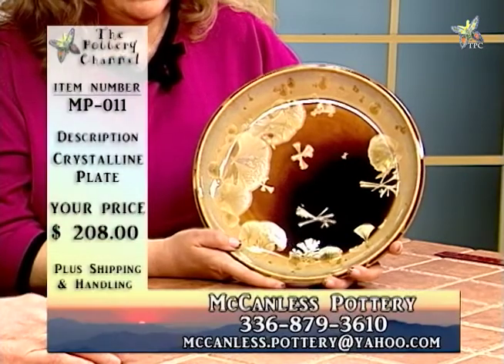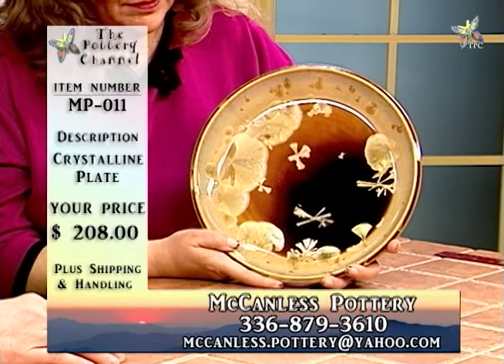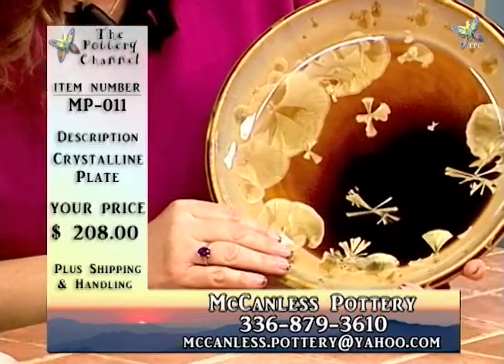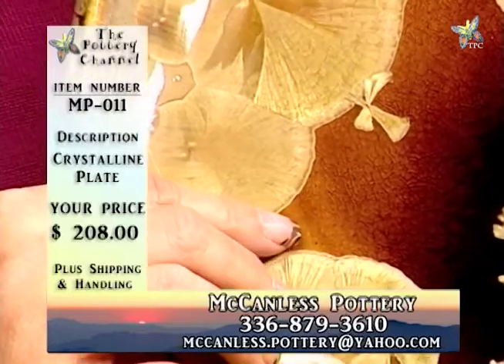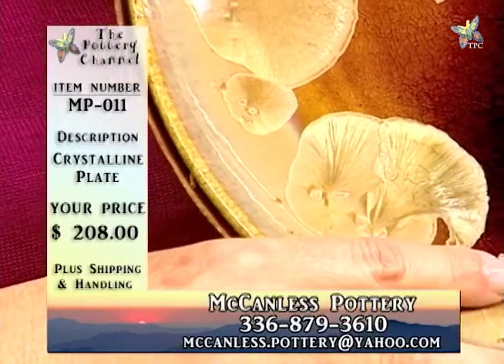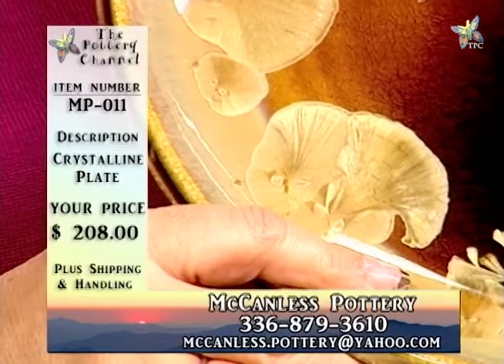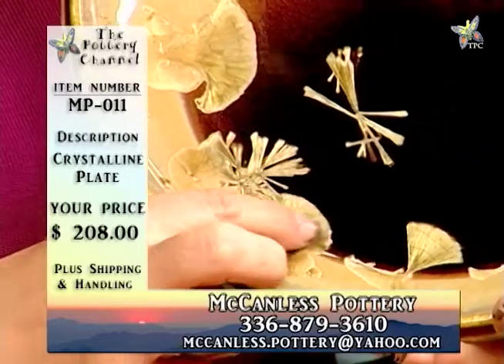This is a process known as the zinc silicate macro crystalline glaze. Essentially what I'm doing is taking zinc oxide, which is a metal, and making a glaze alongside silica, which when it reaches a certain temperature will become a glass. Right around 2350 degrees Fahrenheit, the zinc oxide and the silica will inherently combine and form a zinc silicate crystal. There are no crystals whatsoever as you apply the glaze — the crystals only occur at right around 2350 degrees Fahrenheit.